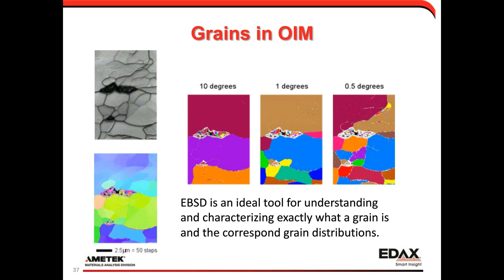If we use a grain tolerance angle of 10 degrees, shown in the middle left, you'll see that the measurement area is broken up into 3 primary blocks of grains: a top, a middle, and a bottom. If we define the grains at 1 degree, we see that the top block is still about the same, even though there's lots of grain boundary contrast in the image quality map. But the middle and bottom grains start to section down into little subgrain, subcell type structures. And if we go as low as a half a degree, now that top grain breaks into different structures. So a lot of times, measuring a grain size will depend on how that grain boundary influences the property of interest, and which of these would be appropriate for modeling in an equation.